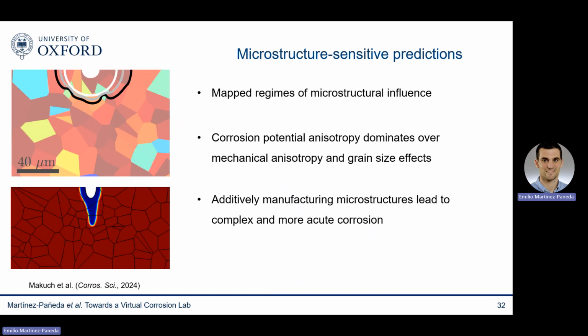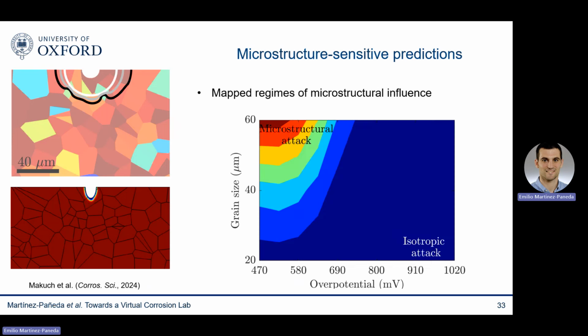One is to map the regimes where microstructure matters. When do you need a full microstructure analysis? So here you can see the type of results we can get. You can build this type of maps where you have grain size on the vertical axis and overpotential on the x-axis, and then we can quantify under which conditions you can get away with a simpler model and under which conditions you need to resolve the role of the microstructure.